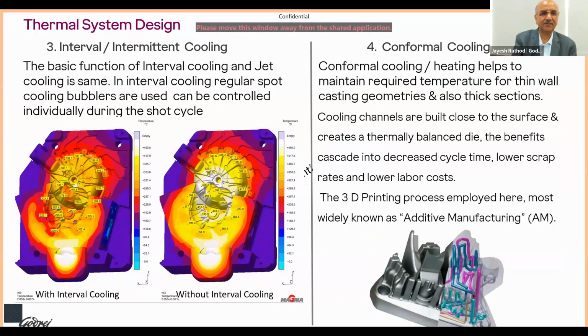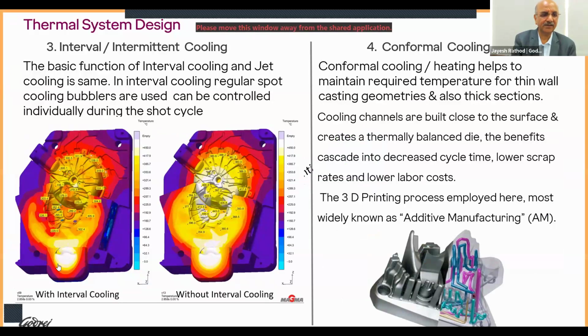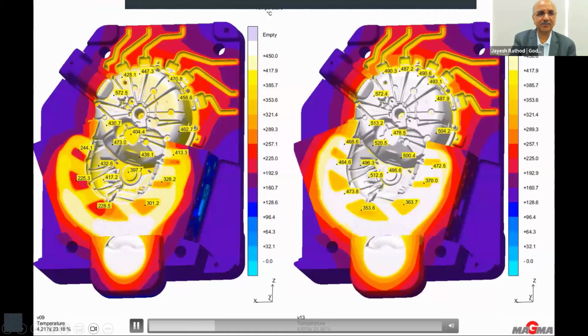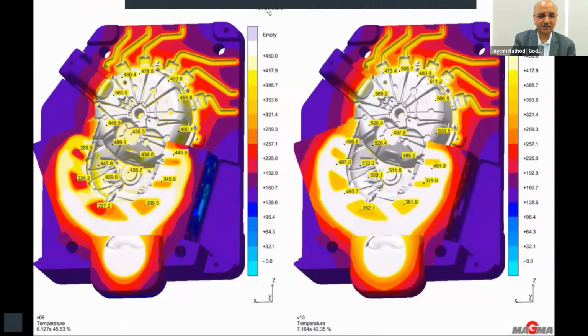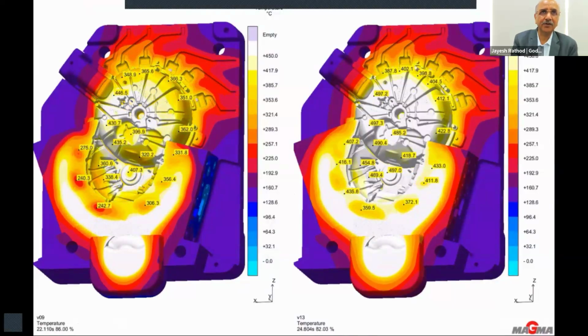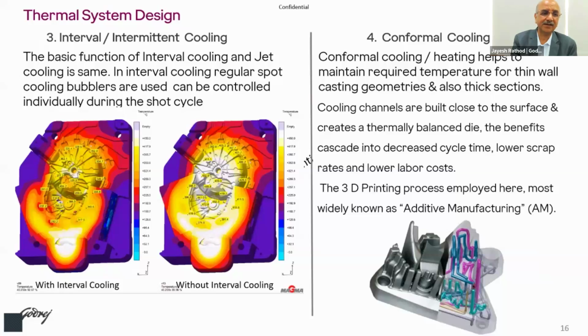There is another method called intermittent cooling. Here the cooling is started and stopped. So you can see how the temperature is getting affected when it is continuously cooled or not cooled, and again when the interval cooling is being used. We can see a difference in temperature of around 70 degrees centigrade. So this helps us to maintain the thermal profile of the die insert when the casting is being produced.